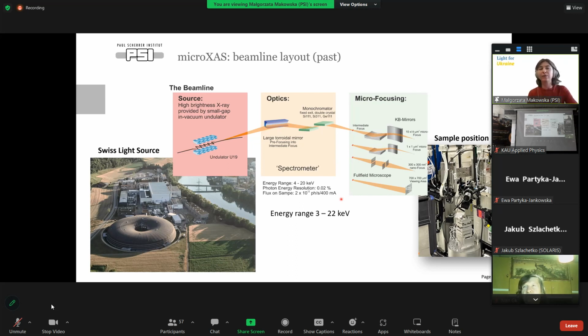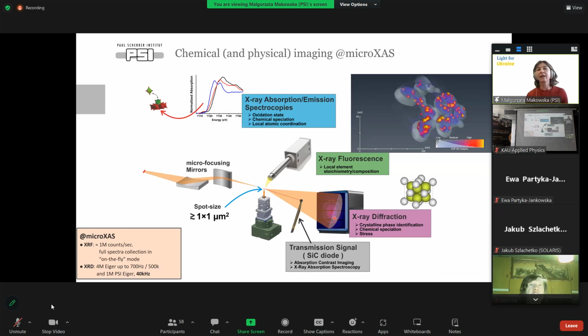Up to now, we were operating in this range of energy from 3 to 22 keV. However, in reality, it was rather between 4 and 20. So that was the usable flux. At the edges, we had very few photons. And this is a sketch of how the final sample position looks.